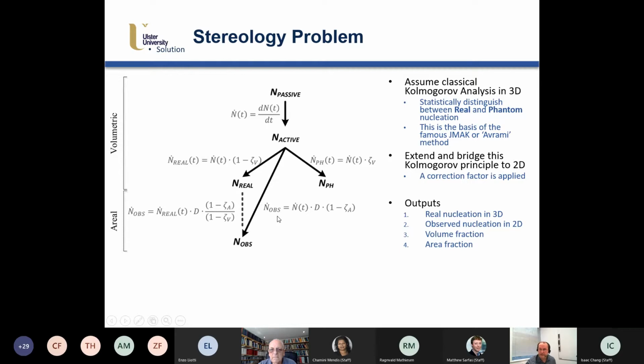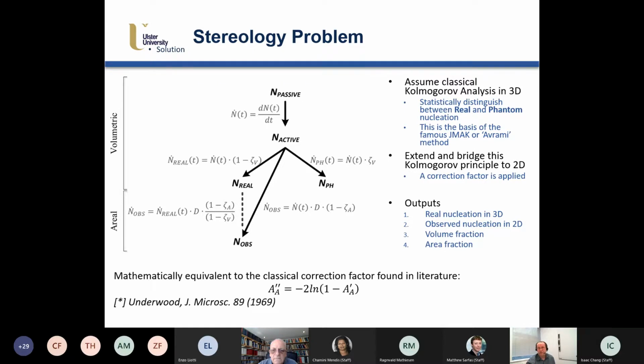Okay, so let's go. The idea here is that there is a way of calculating the number of observed in the 2D plane. And so the outputs here are real nucleation in 3D, observed nucleation in 2D. You get volume fraction and area fraction. And with all of this information, you can construct the complete picture. So we compared this then to some of the classical stereology. Underwood had some correction factors, and if you break it down, you can show that they're equivalent.